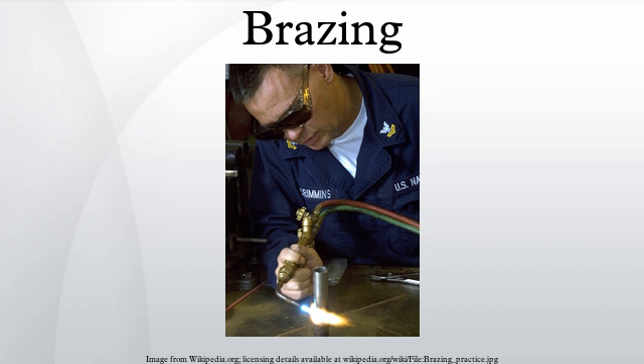Eutectic alloys melt at a single temperature, without mushy region. Eutectic alloys have superior spreading. Non-eutectics in the mushy region have high viscosity and at the same time attack the base metal, with correspondingly lower spreading force. Fine grain size gives eutectics both increased strength and increased ductility.